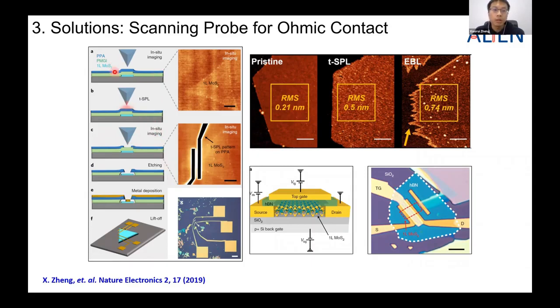And PMGI also has very unique features. When we do the undercut etching, the PMGI can also be removed completely. If we look at the surface quality after processing compared to electron beam lithography, where we normally observe residue of PMMA, in our TSPL method we can greatly preserve the quality of the surface. And because the tip never touches the materials, we wouldn't have any damage to the surface. And one unique feature is that in this process, we actually introduce a certain doping effect in the contact region. That's another very important reason we can improve the contact quality.